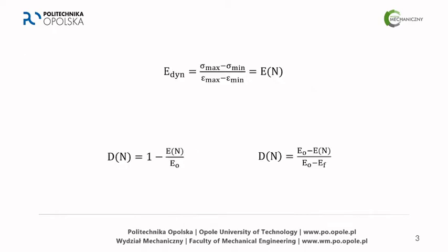However, some researchers already found out that it's not a good idea to use the constant modulus for composite materials. So they suggested that we could use a dynamic value which changes when the cycles increase. Here at the top of this page, we can see the equation for this dynamic Young modulus. And then when we analyze the degree of damage, there are 2 propositions at the bottom of this page. They come from 2 different articles.